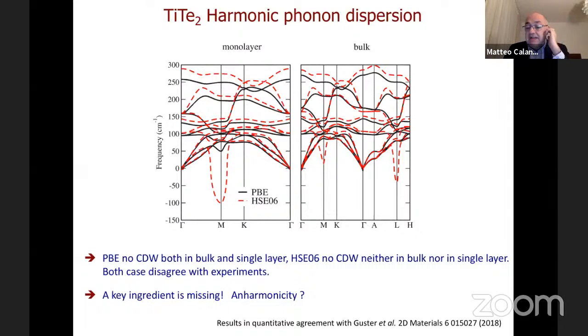These results are also in qualitative agreement with another paper of Guster, which made the authors speculate that strain was the key mechanism to explain this difference. However, starting from HSE06, to remove the instability in the bulk and keep it in the monolayer, you have to apply a substantial strain, which is very large. It is hardly obtainable in experiment. So another possibility would be that what is missing is anharmonicity.